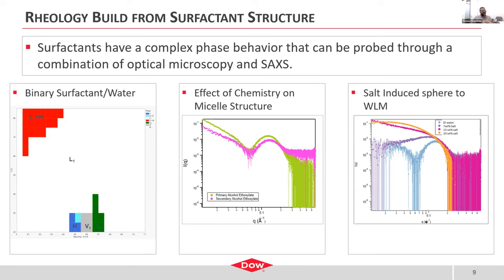And what you can do by the addition of these electrolytes is you can change the local self-assembly of the surfactant and cause them to form elongated, what are called worm-like micelles. What makes these worm-like micelles really interesting is not only that they're long rods, but they are actually of a length where you can get entanglement between the rods. And that entanglement between these micellar rods gives rise to an increase in viscosity.